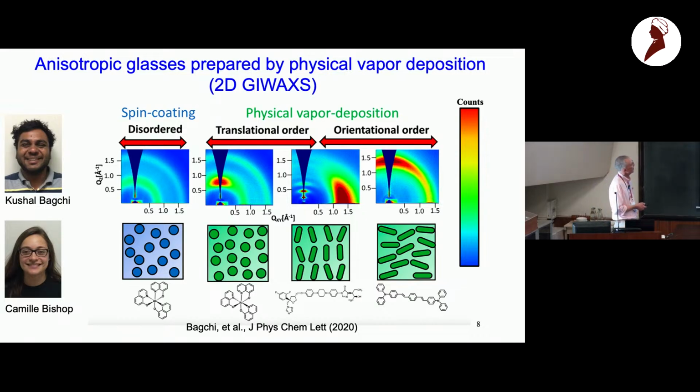Okay, cool. There's extra scattering here, and the Q value of this scattering tells us that there's some sort of layering of these spheres in this deposition. So qualitatively, it looks something like this. If we deposit rods, they might decide to lie down, in which case the scattering looks like this. You can think about this as basically the nearest neighbor distance here. In this direction, there's a lot more nearest neighbors at that distance than in this direction. That's why there's a lot more scattering here than here.